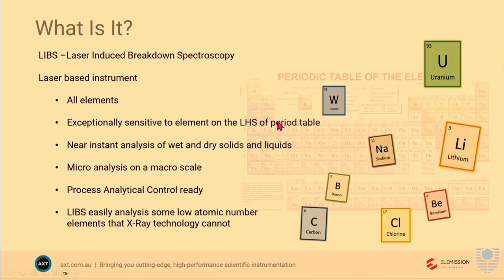It's very difficult to analyse. You can analyse beryllium and you can get instruments that analyse boron, but there's no instrument out there that analyses lithium. So with X-ray technology, you're least sensitive at the top of the periodic table, more sensitive as you go down. With LIBS, you're more sensitive to the left-hand side. It's a near instant analysis, so it's the speed of light.